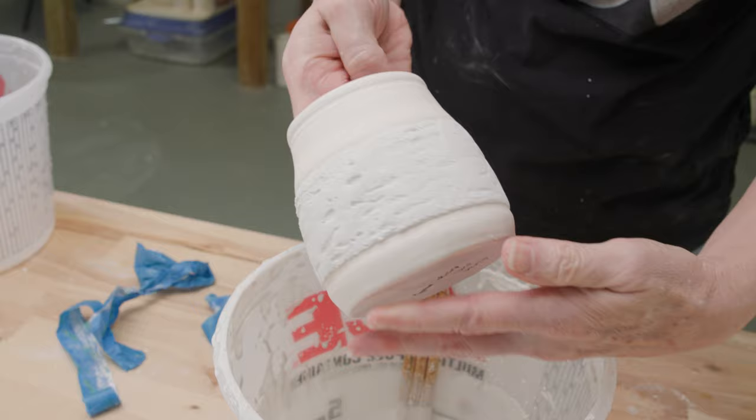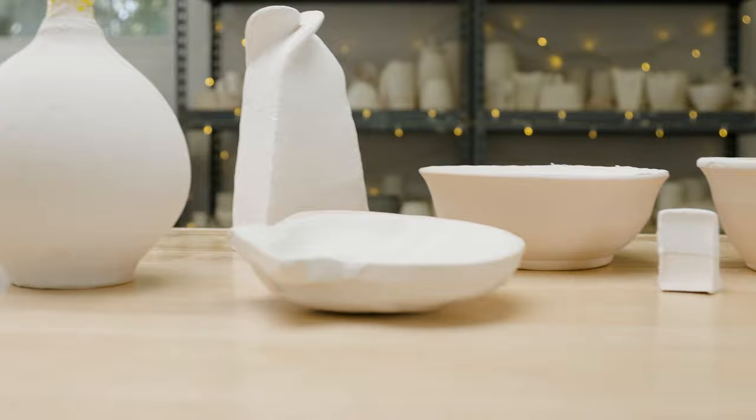On this vase, we decided to test to see if thickness made a difference to the look of it. On the first side, I brushed on one layer of glaze only. On the second side, I brushed two layers. On the third side, I brushed three layers and let that dry. Jim and I cleaned them up and even added some other glaze to a few of them. I put them all in the kiln and fired them to cone 5. When I took them out of the kiln, you can hear them start to ping — this was the crazing or the crackling of the glaze.